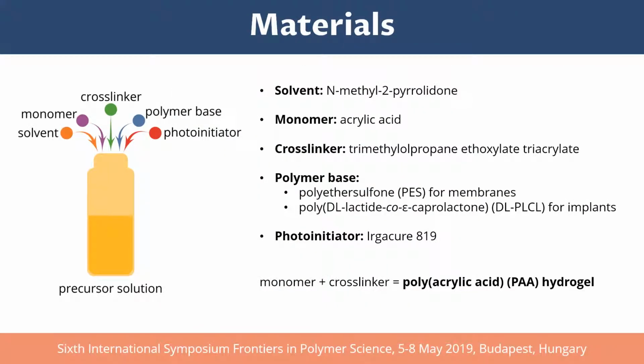What materials did we use for the fabrication of composite reservoirs? We first prepared the precursor solution by dissolving all functional components in a common solvent. Monomer and crosslinker were used to produce the polyacrylic acid hydrogel, while the polymer base will later become a hydrophobic matrix. Note that polymer bases are different for membranes and implants. Photoinitiator is required for photopolymerization under UV irradiation. With these materials, we perform the synthesis comprising two main steps.